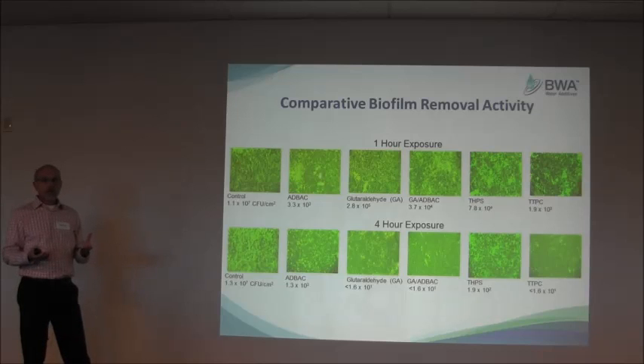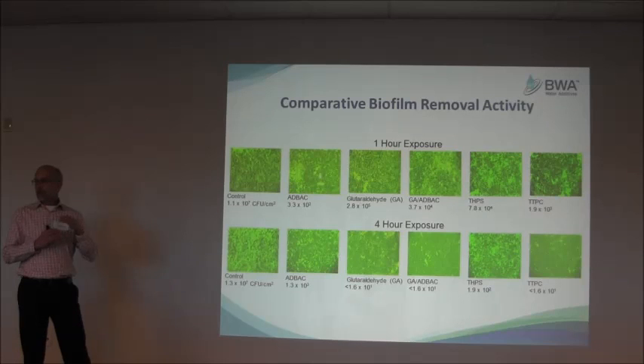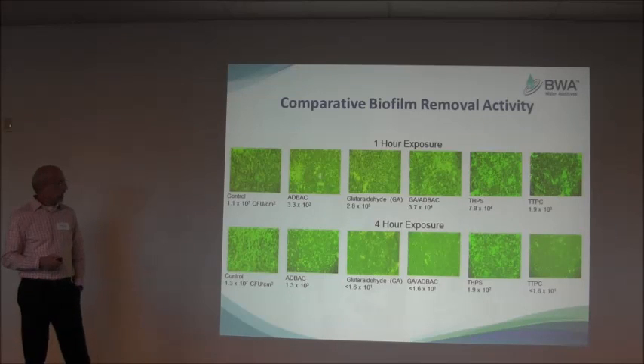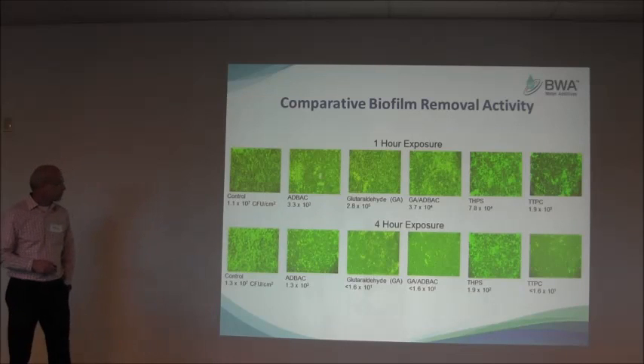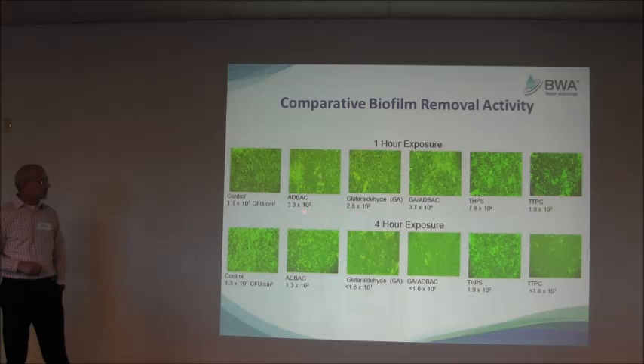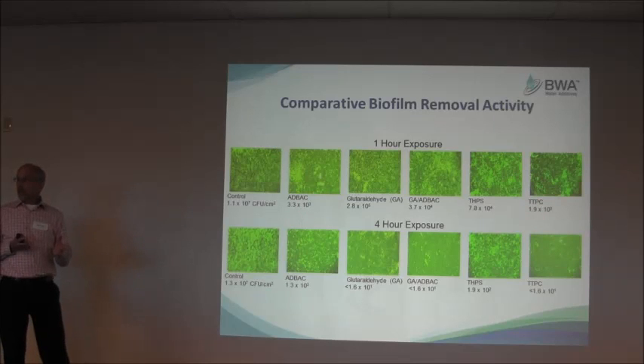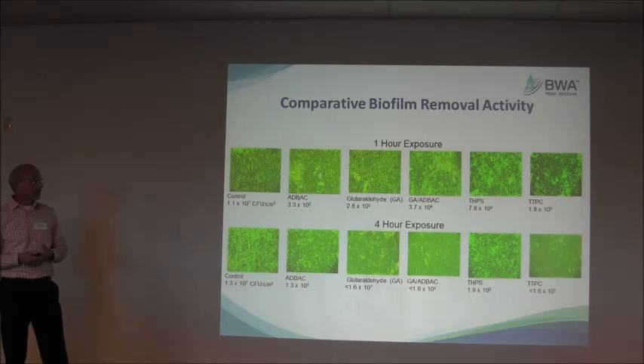Why would you want to remove the biofilm? Residual biofilm is going to prevent corrosion inhibitors from getting to the surface. Your corrosion inhibitor release program is going to be a lot more effective if you not only kill the biofilm but remove it. Some of these products are surfactant-like molecules — your ADBAC-type product and TTPC — and they do tend to work a little better at removing the biofilm.